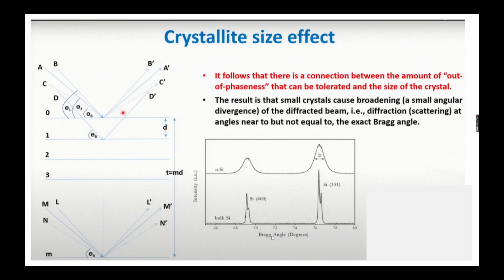So here, as you can see, the result is that small crystals cause broadening. When you have a crystal which is small, that will cause a broadening of the diffracted beam. That is diffraction at angles near to but not exactly at the right angle. So here you can see a difference. This is bulk silicon. This is amorphous silicon. For these, because the crystallite sizes are different, you will have a difference in the broadening. So when you have a smaller crystal, that will cause more broadening.